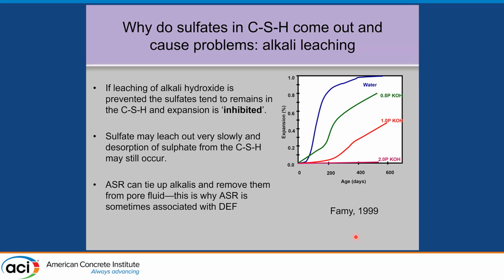If alkali leaching is prevented, sulfates tend to remain in the CSH and you don't get any expansion. This is work that Charlotte Famy did. She was working with Karen Scrivener at the time. They were doing her PhD about the same time as Terry did. And you see that in a high potassium hydroxide solution, there's no expansion.